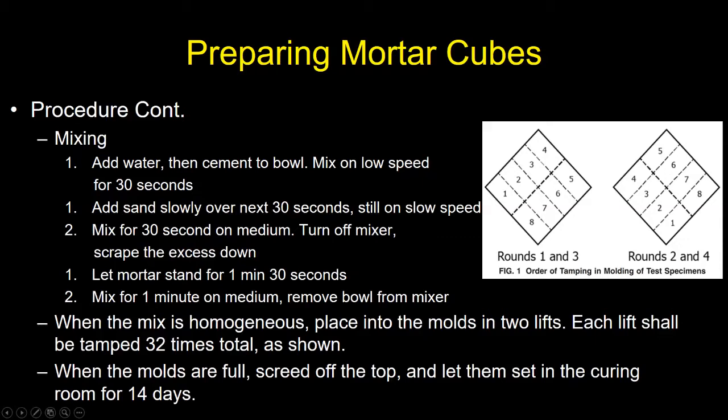After that, you turn it off, and you scrape the excess mortar that's on the sides down into the mess at the bottom of the bowl, just so it's together, and then you will let it stand for 1.5 minutes, and then you'll mix. After that 1.5 minutes, you'll mix for another minute on medium. After that, you remove the bowl from the mixer and you're done with mixing.